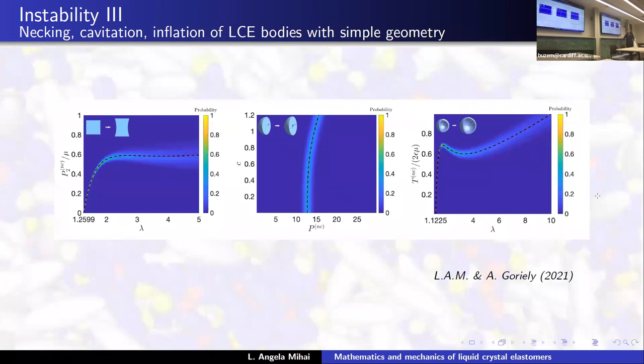But what's so interesting here? Well, the interesting fact is that in order to straightforwardly compare the theories between the two, you need the correct way of expressing the stresses in the liquid crystal elastomer from the stresses of the rubber network. If you were to do this analysis from scratch with the liquid crystal elastomer strain energy function, it would be a very difficult type of calculation. But if you correctly incorporate the rubber theory into the model and the way the derivation is produced, this can be done very quickly. So it's a hard way of doing it, and it's an easy way of doing it. We had a sort of easy way of doing it in the paper. We treated them together because it was the same framework, and it's valuable to have a framework that can treat all these instabilities in a very similar way.